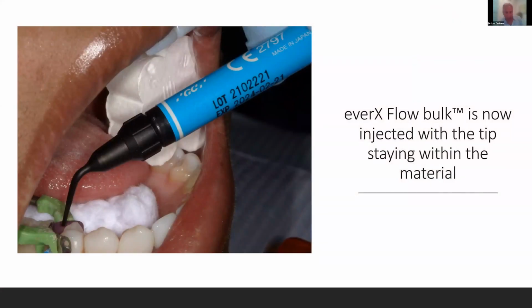Now I'm going to place everX Flow bulk. You place the tip inside the material, and you must keep the tip inside the material as you're injecting, just like a flowable. You don't want to create any air bubbles. So inject slowly, and it kind of comes out like Vaseline. You're going to need to give it about 10 seconds to self-level. You can even start packing it with a micro brush after about 10 seconds.